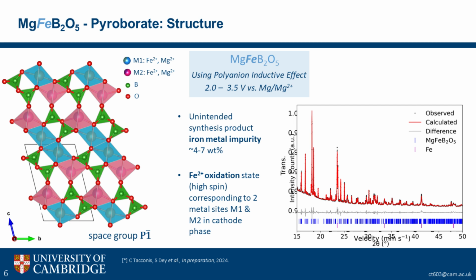And here you can see the synchrotron powder X-ray diffraction collected of the material, where we were able to refine the crystal structure. And we identified a small iron impurity that was coming as an unintended synthesis byproduct from our synthesis route. And it ranged between 4 and sort of 7 weight% based on the synthesis.